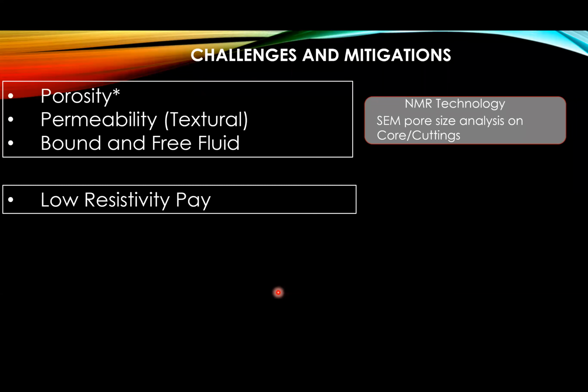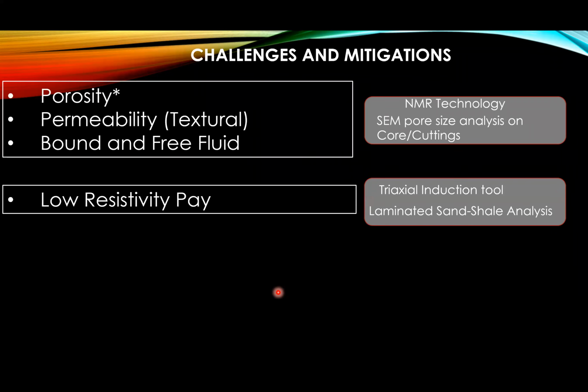And then low resistivity pay. For the low resistivity pay, as I said, it could be very integrated with fine laminae of clay, which lowers the resistivity. So we generally propose to run what we call a triaxial induction tool for a laminated sand-shale kind of analysis model. All these major service companies have this induction measurement. We have one slide. We'll look into that a little bit more.